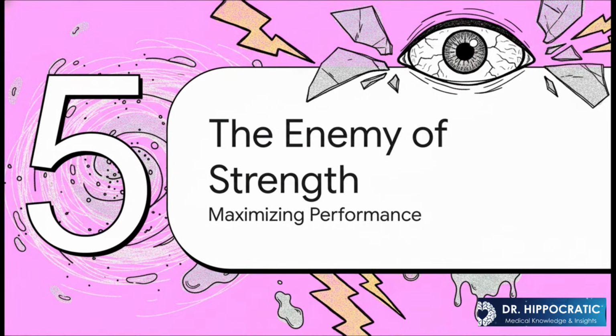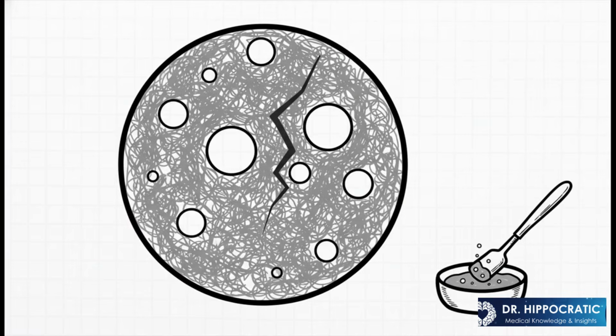So, we know the powder-to-liquid ratio is huge, but there's one last critical factor that decides the final strength of a GIC restoration. Let's talk about the true enemy of GIC strength. And that enemy is one word: porosity. We're talking about tiny little air bubbles that get trapped when you're mixing it. Every single one of those bubbles is a weak spot, the place where a crack can start. That's why careful hand mixing is absolutely essential to keep those bubbles out and get the maximum strength.